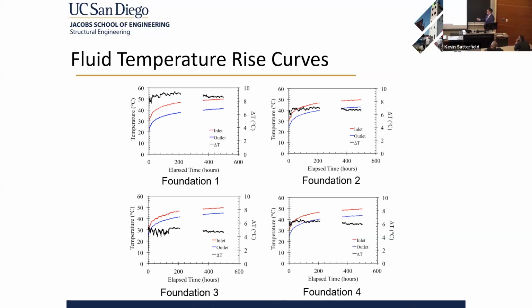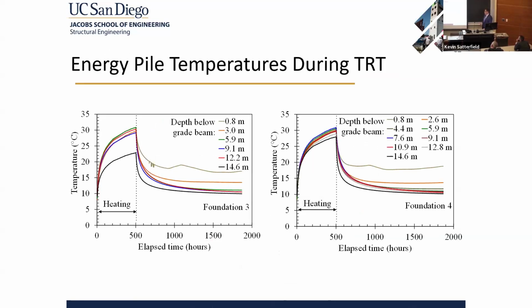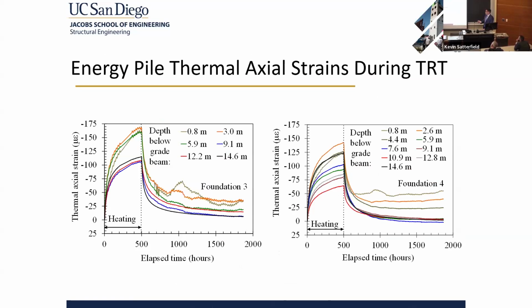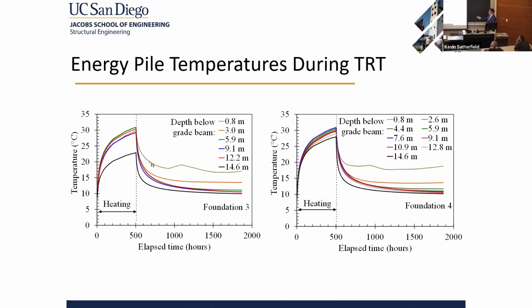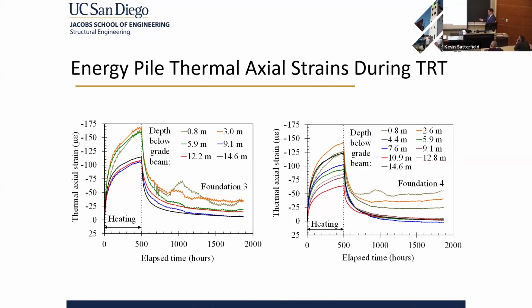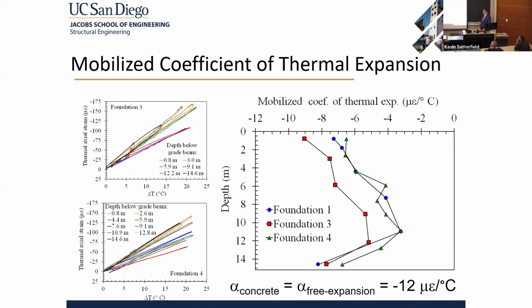We did our thermal response tests where we had a constant flow rate. Temperatures of the piles increased, and then the difference between the temperature inlet and outlet tells you the heat flux into the pile. Then we can look at the temperatures of the pile themselves. They're generally pretty uniform with depth, except near the surface. And then these are the strains that were measured. These are definitely much less uniform than the temperature. So the temperature is relatively constant with depth, but the strains are variable. And this is due to the soil structure interaction.